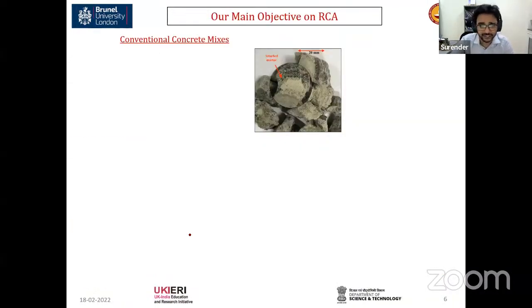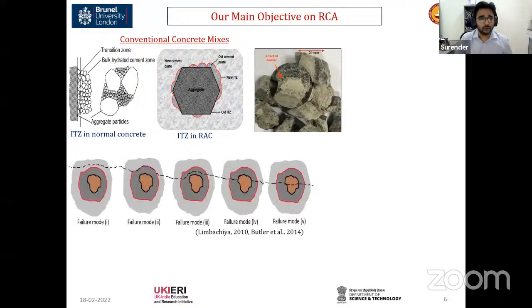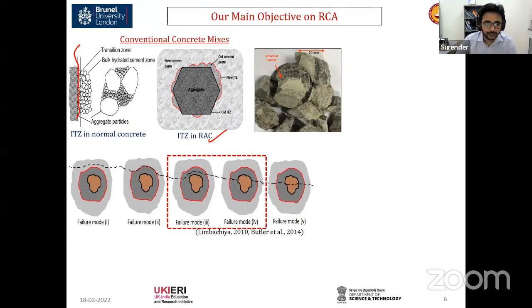Like Rohit has already mentioned, in the case of normal concrete, there is only one interfacial transition zone. When you apply any loading, the interfacial transition zone being the weakest link, the crack will propagate through it. But in the case of recycled aggregate concrete, when you are using recycled concrete aggregates, there could be different failure patterns. Mostly mode 3 and mode 4.